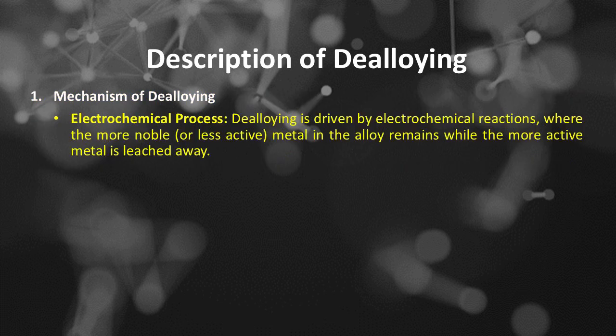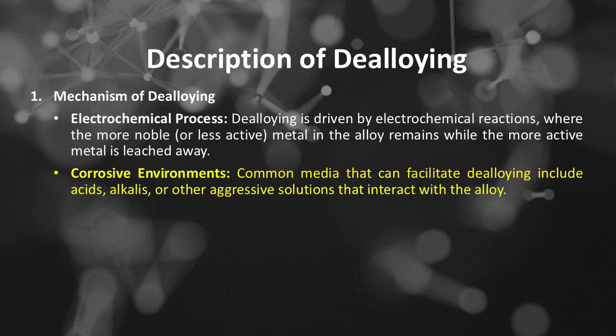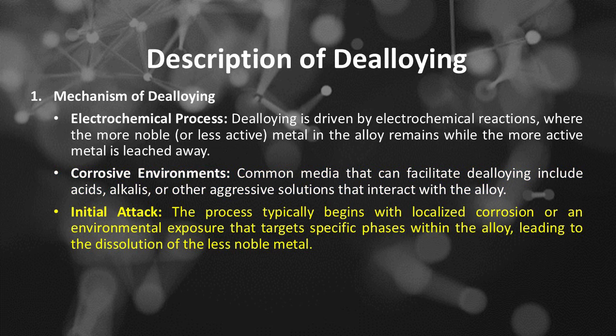Electrochemical process. Dealloying is driven by electrochemical reactions, where the more noble, or less active, metal in the alloy remains while the more active metal is leached away. Corrosive environments. Common media that can facilitate dealloying include acids, alkalis, or other aggressive solutions that interact with the alloy. Initial attack. The process typically begins with localized corrosion or an environmental exposure that targets specific phases within the alloy, leading to the dissolution of the less noble metal.